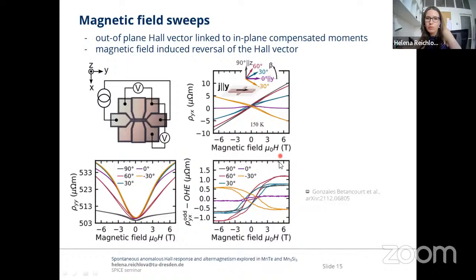The out-of-plane Hall vector is linked to the in-plane manganese moments of the manganese telluride. And with the external magnetic field, we are capable of reversing the Hall vector and therefore measuring this anomalous Hall effect. The important point is that the out-of-plane component of the external field is the important one, because we see that, for example, sweeping along 30 degrees and along minus 30 degrees, which in principle has the same projection of the magnetic field into the in-plane direction and opposite to the out-of-plane direction, indeed gives the opposite anomalous Hall effect, showing that this is the out-of-plane component of the external magnetic field which matters.